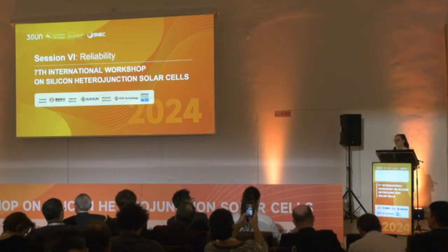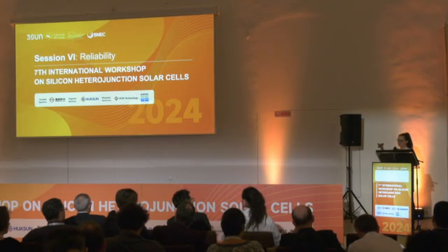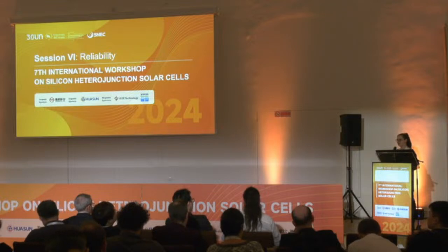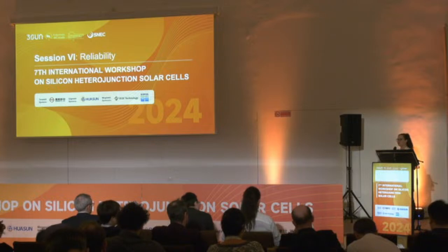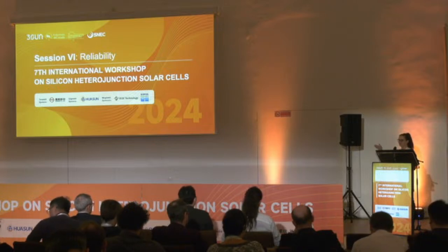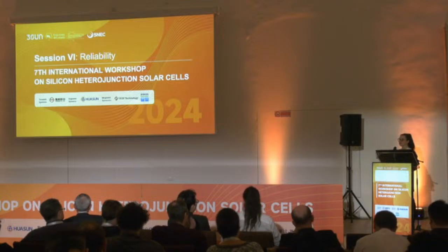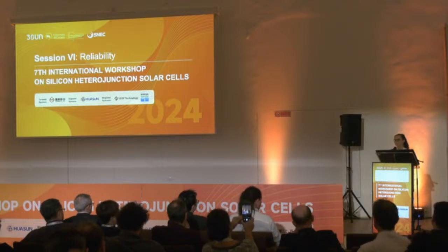So yeah, that's an interesting question, and they are two different systems that were analyzed there. The one that had the UV blocking additive was not the same one that was being analyzed for microscopy, and the module that was analyzed by microscopy did not have a UV blocking encapsulant. So that one had UV pass encapsulant for the one that grew the silicon oxide. The one in the field with the UV blocking encapsulant, we have not cored it yet. Okay, yeah, thank you, thanks a lot.